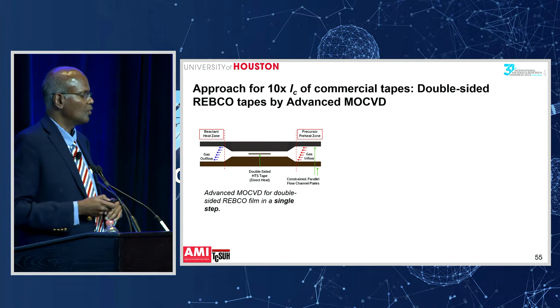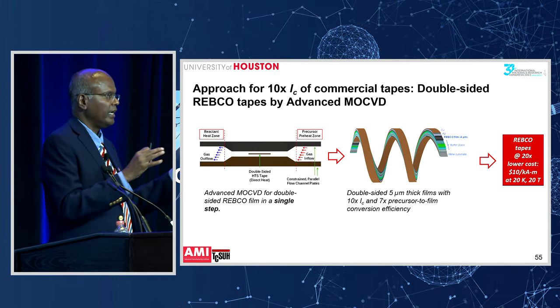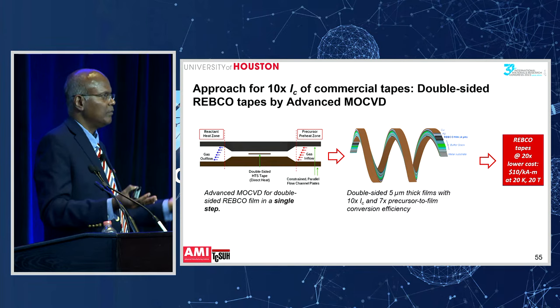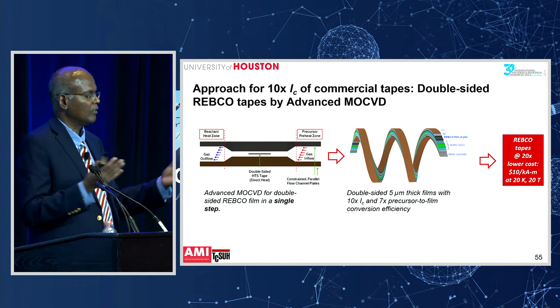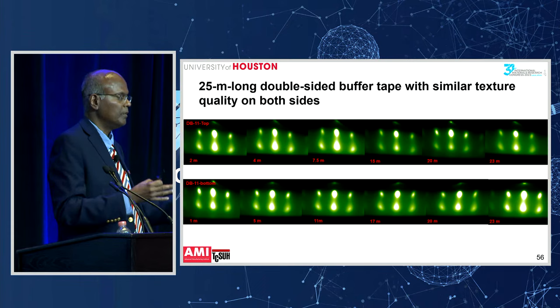The beauty of the advanced MOCVD process is that there's no heater, there's no shower head, which means you can coat both sides simultaneously in one pass. So you're not adding any more material to the process. With the same material, you can coat both sides. So that is the idea. And before you coat the superconducting film, you need to coat the buffer layers, right? The buffer layers have to have good texture.